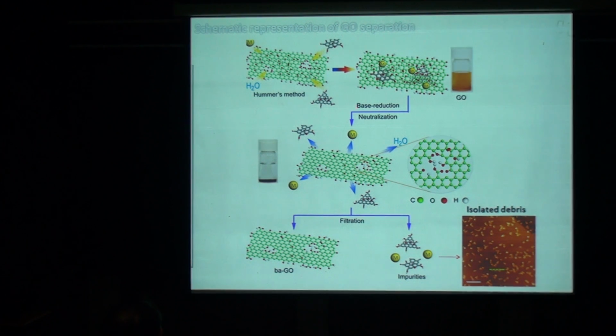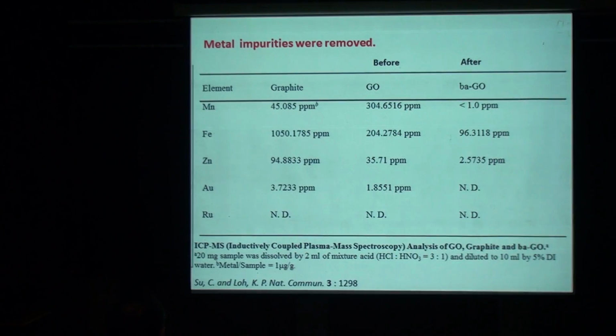We have to do a base treatment to wash away this oxidative debris. Otherwise, you coat the entire graphene oxide and give it a very high oxygen content, but actually it's not due to the graphene, it's due to this oxidative debris. You do a base treatment, remove it, and do a neutralization, and regenerate a very potent material. We call this base-acid graphene oxide. Base treatment followed by acid treatment, graphene oxide, we call it BAGO. We have made a patent on this. These are very highly active catalytic materials.